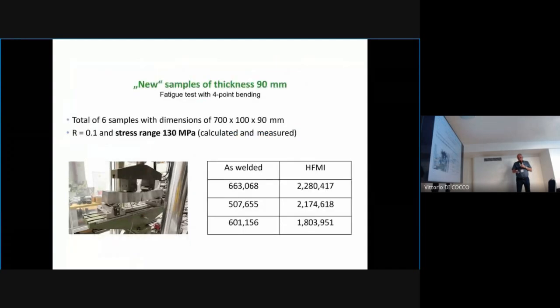That part of the investigation was the testing of so-called new samples of thickness 90 millimeters. We prepared for bending. You can see that the stress range was 130, calculated and measured. You can see asymmetry of cycle, and you can see results of a number of cycles for as-welded version and version with application of HFMI. You can see that the fatigue life is higher, 3 to 4 times more.